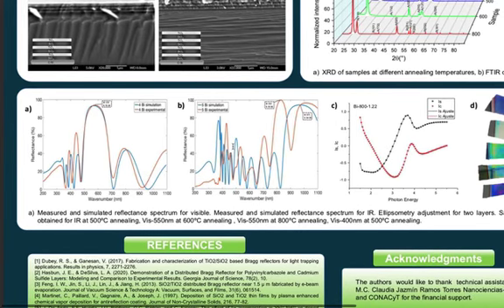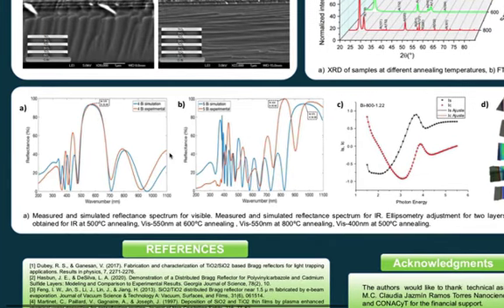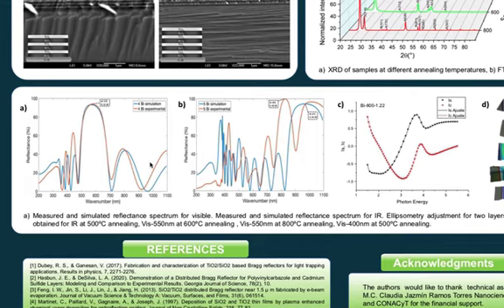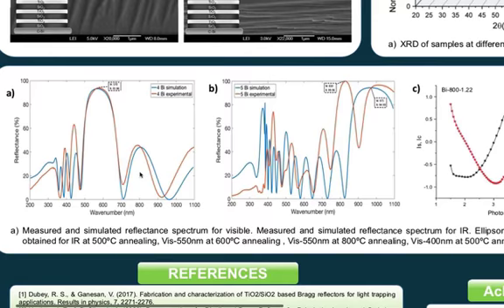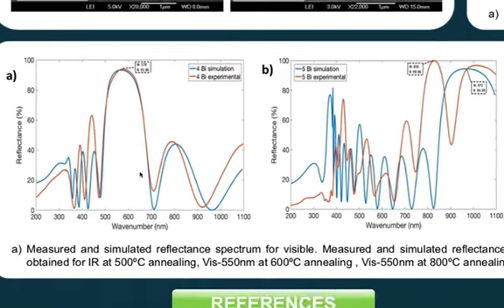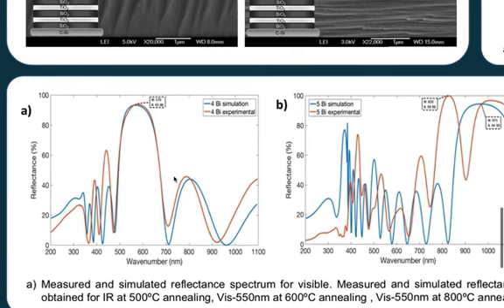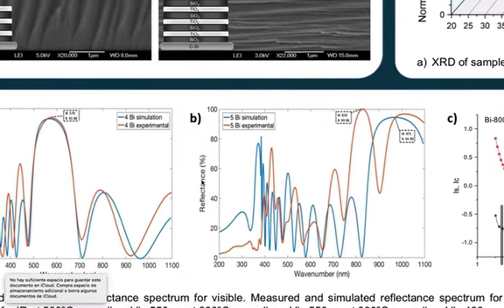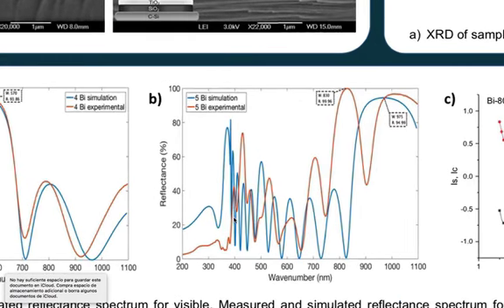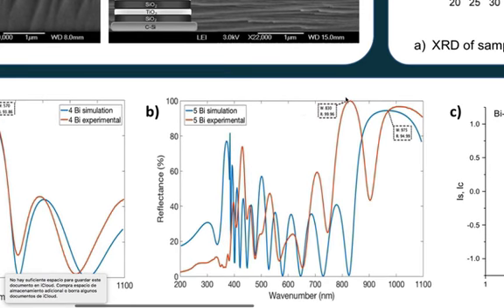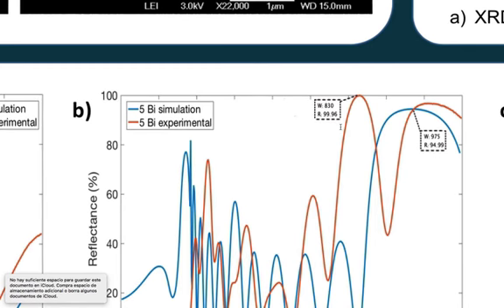Well, we use spectral ellipsometry to obtain the values of the refractive index and the layer thickness at different annealing temperatures, finding that the theoretical model predicts the reflectance behavior for thin layers in the visible range, but fails for thicker layers in the higher range, due to the increase of the porosity of the layers. However, a reflectance greater than 95% is obtained in the area of greatest interest.